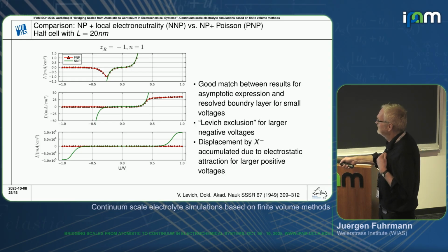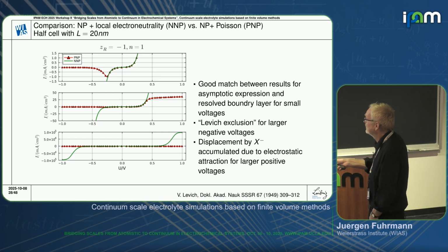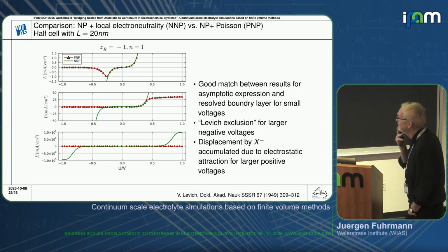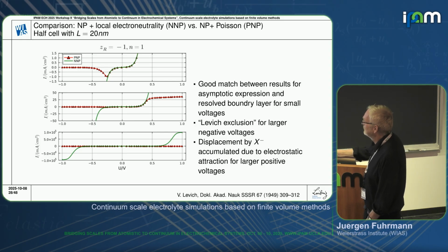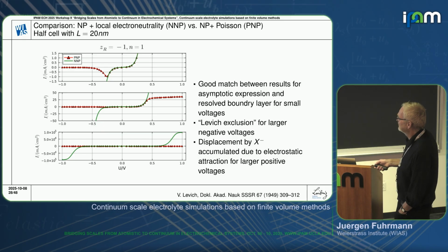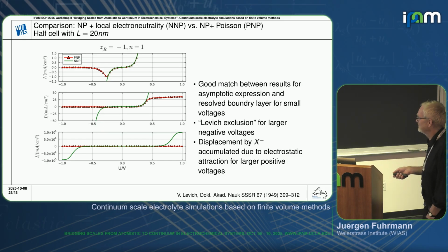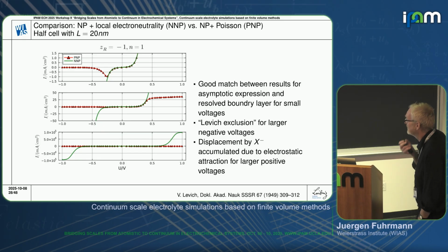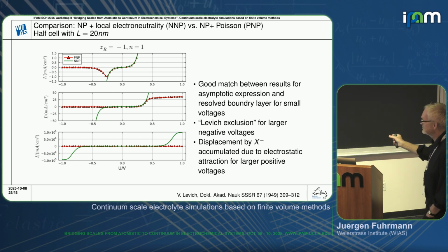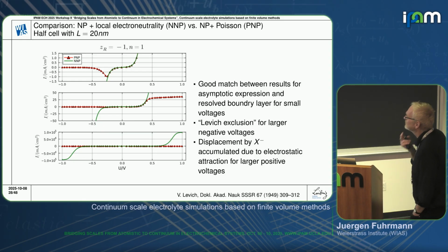But we get other effects if we increase the potential. In particular, we get Coulombic interactions, which are not part of this collapsed double layer model, which lead to a decrease of the reaction rate if we further increase the potential. Some people call this so-called Levich exclusion in the literature. It seems to be seldom mentioned in electrochemical experimentation, but I have seen it mentioned in papers by the Compton group. This is an effect which kicks in at larger potentials, and it would be interesting to see more about this and to discuss it more. At very large potentials, these are always the same calculations, but on a different zoom scale of the y-axis.